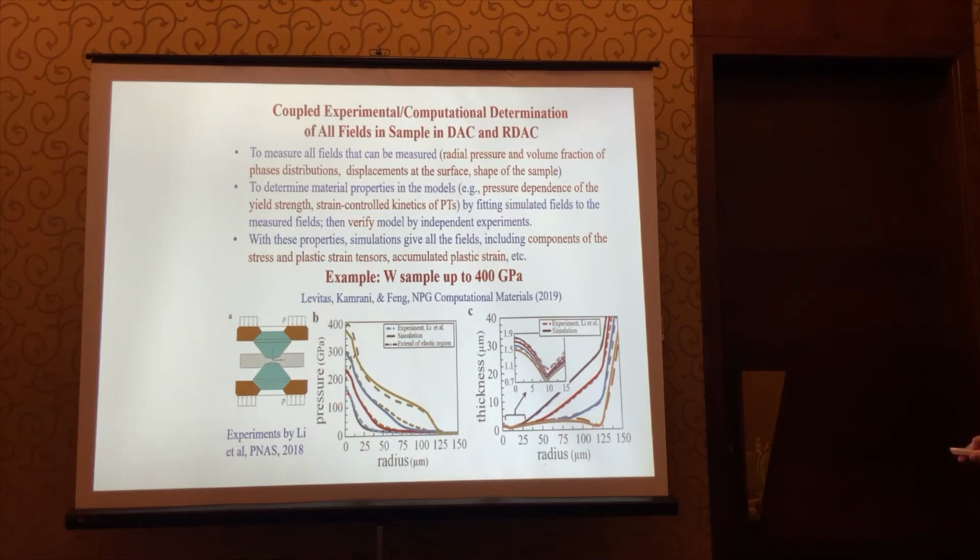And we use two lower pressure distributions to calibrate our model, including friction and yield strength, and then two upper higher pressure distributions and four sample thickness profiles to verify our results. And you see very good verification, despite the fact that we did not use any of geometric parameters for calibration.